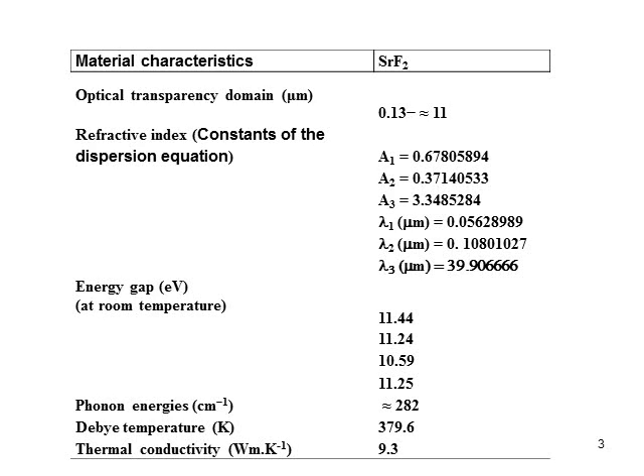In addition, its dispersion equation is well known in the literature, and we have the values of the refractive index at any wavelength. This compound is also considered to have very low phonon energies. Therefore, this property gives it a great advantage in emission spectroscopy. It also has a very acceptable thermal conductivity, since it is close to those of materials that gave the laser effect, such as YAG and fluorite CaF2, or almost 10 watt per meter per Kelvin.